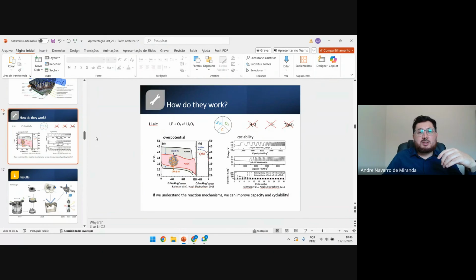So this is one of the results. Another result is the confirmation of the mechanism of formation of lithium peroxide. We could see that the adsorption is preferential in the oxygen vacancies. This is a nice result, and the reaction starts there. So the cobalt is a reaction site, a nucleation site for the peroxide in the system. These are the two main results that we could understand.